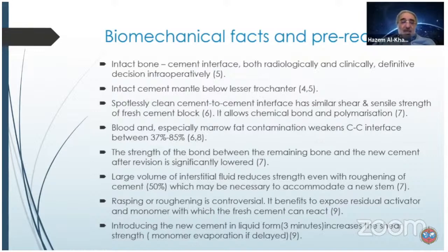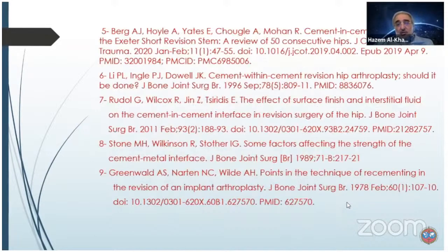You have to have very clean surfaces. And you also have to introduce the cement in the liquid form and pressurize it in that form, because this will give better strength, and it also allows for the polymerization and reaction between the polymer and the residual monomer.